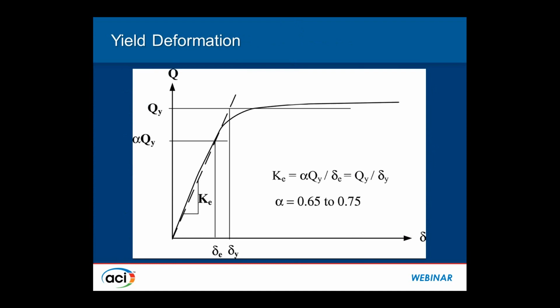One such technique is shown. We all know that yield level and ultimate capacity are close, and one may use nominal capacity expressions to analytically predict this yield force level. And then if we draw a line between the origin and anywhere between 65 to 75% of this calculated capacity, where these two lines intersect is a fairly good estimate of yield displacement. One can fine-tune this yield displacement during testing, or even better, if there was earlier a monotonic test done, then you would know fairly accurately where the yield level is.